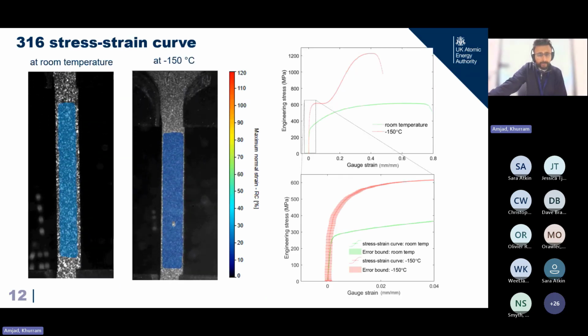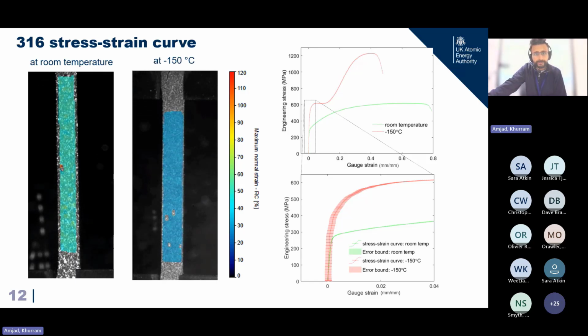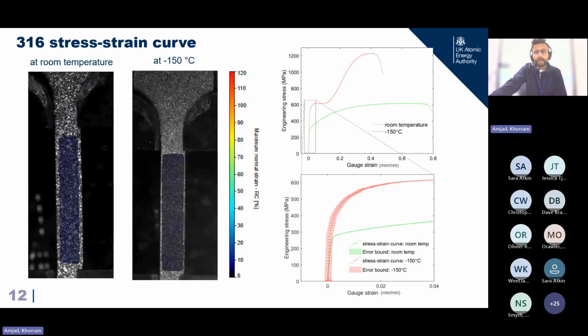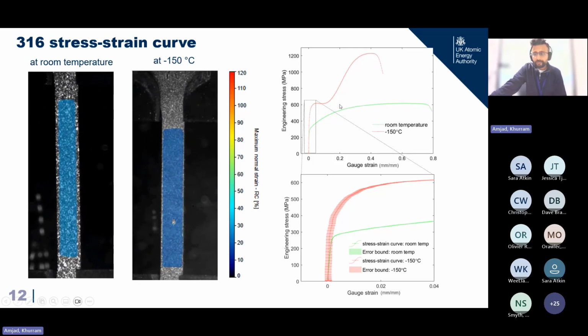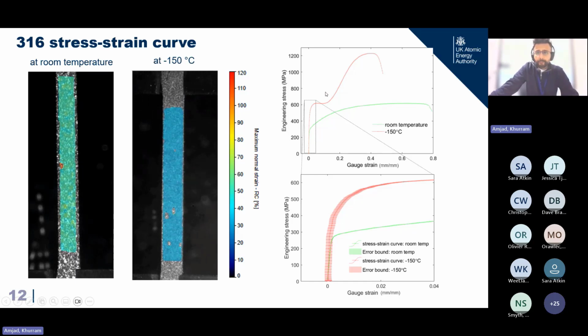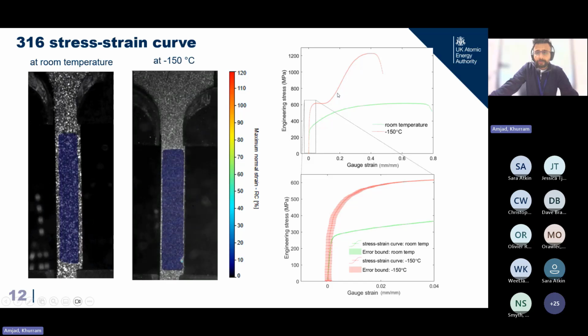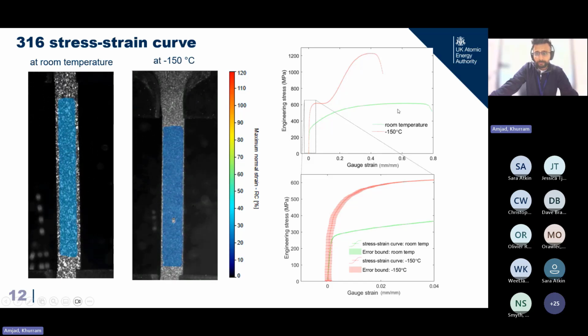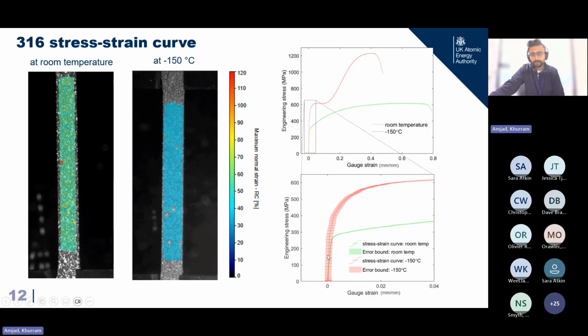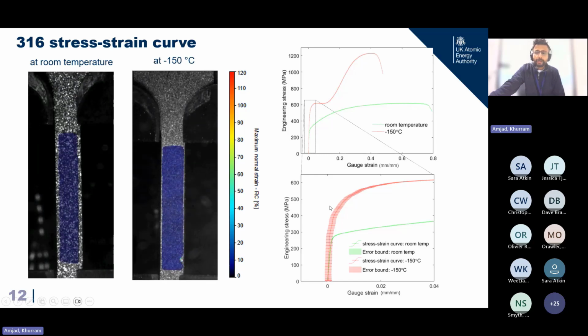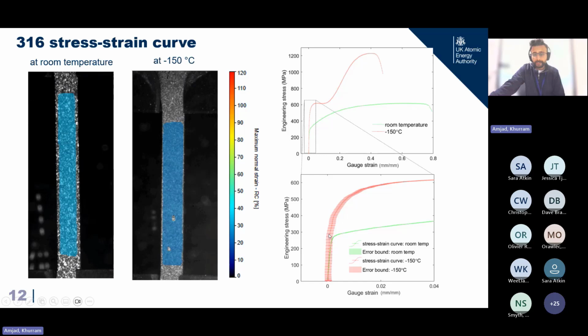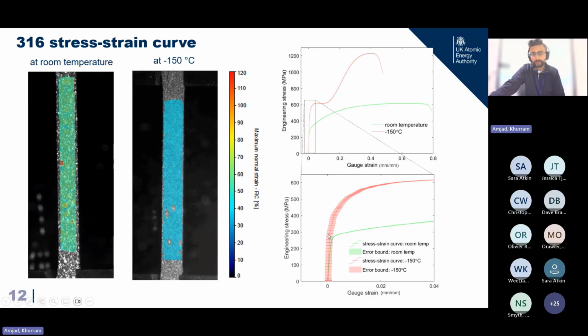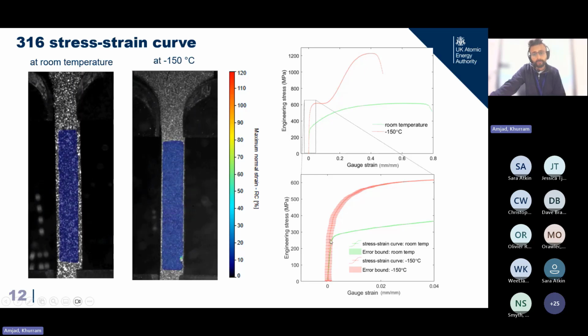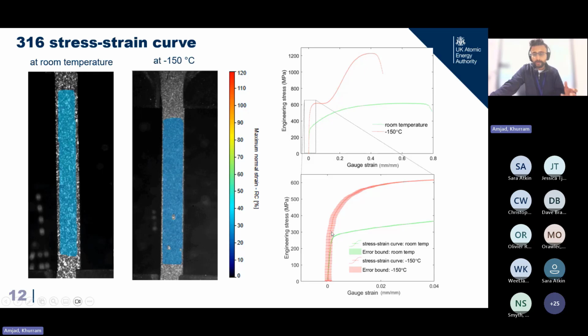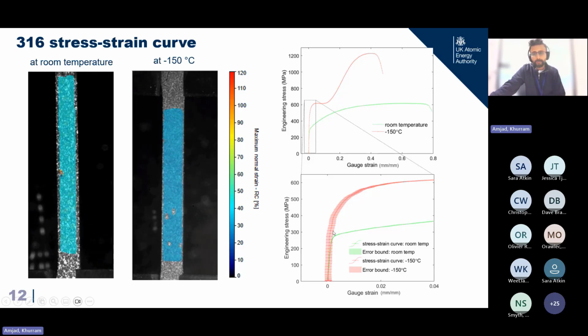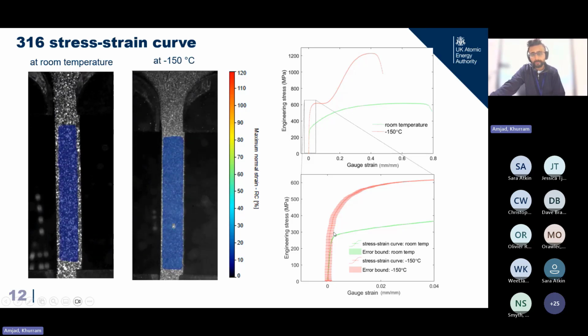These are some of the results we generated from a 316L sample at room temperature and at minus 150 degrees centigrade with DIC. You can see on your right these stress strain curves. The red curve represents the stress strain curve at minus 150, and the green one is at room temperature. We did some uncertainty quantification to work out these error bounds in the strain values. The uncertainties in strains are significantly higher compared to room temperature because of the convection effect. Even though we have computer fans helping with the uniform flow across the sample, we still have higher noise compared to room temperature.